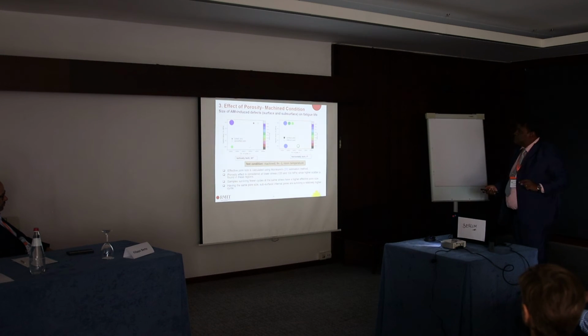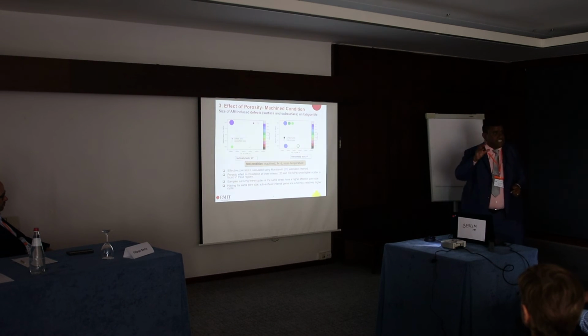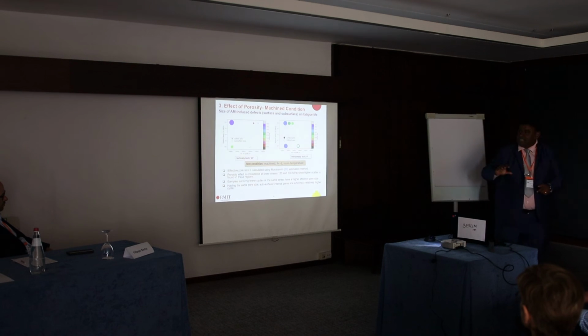Why? Because the pore here is a smaller pore, and the pore here is a larger pore, which controls the fatigue failure in this specific case, which we have been seeing. I will explain this probably and then conclude. What it shows you is the synergistic effect, which we try to investigate in more detail.